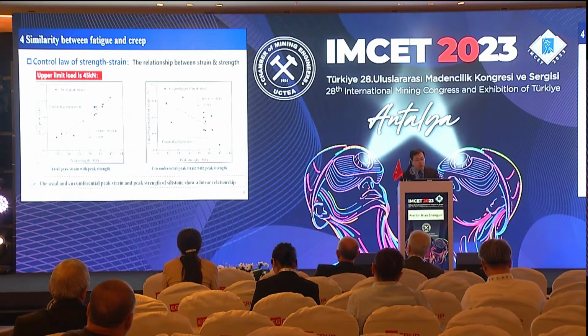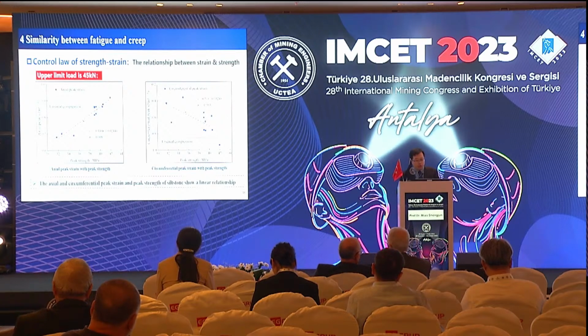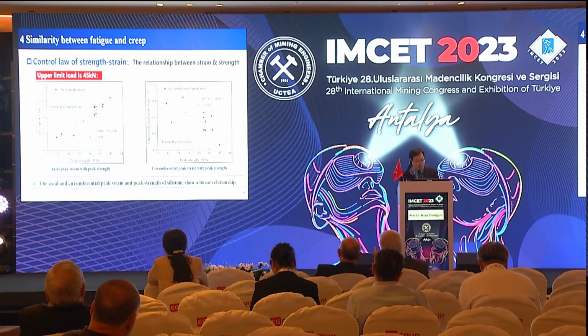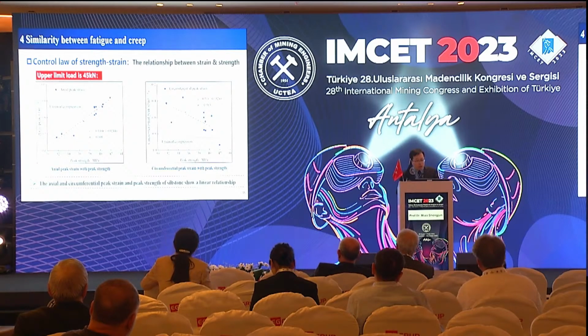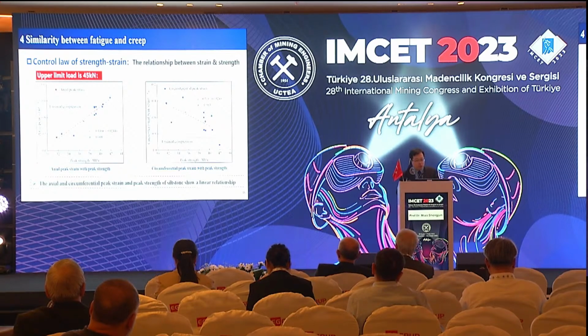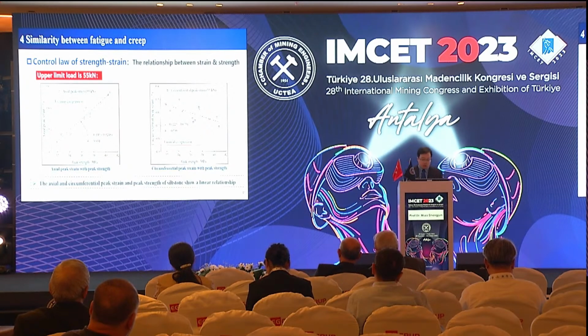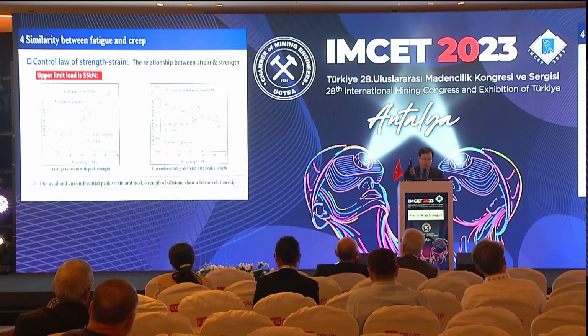Next, we analyze the relationship between the peak strain and the peak strength of the siltstone. From the test results with the upper limit load of 45 kilonewtons, it can be observed that the axial peak strain and the volumetric peak strain show a good linear relationship with the peak stress of siltstone after the cyclic load. In other words, with the increase of the cycle number, the siltstone's peak stress increased with the peak strain. Similarly, the test results of the upper limit load of 55 kN follow the same law. All these results indicate that the ultimate strain of the rock prevents the unlimited increase of the peak strength after cyclic loading.